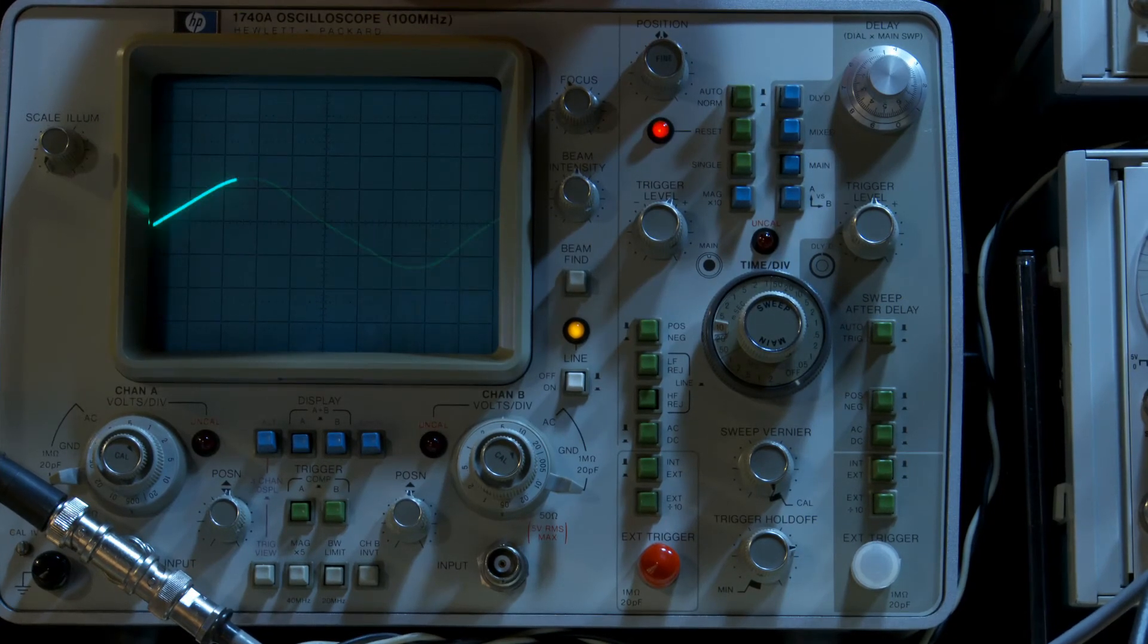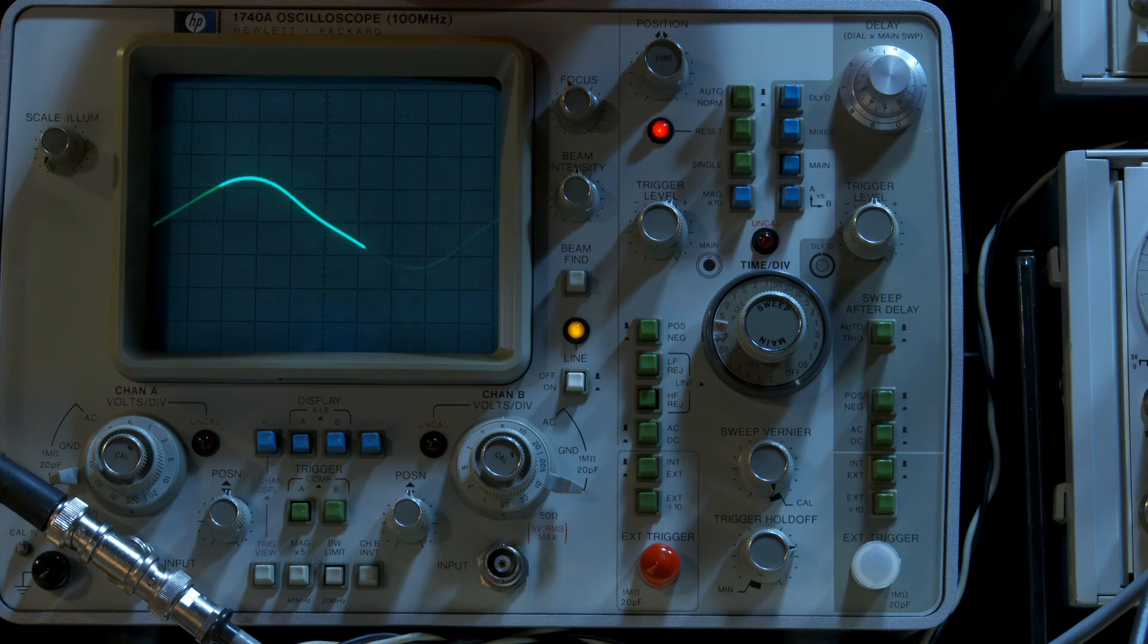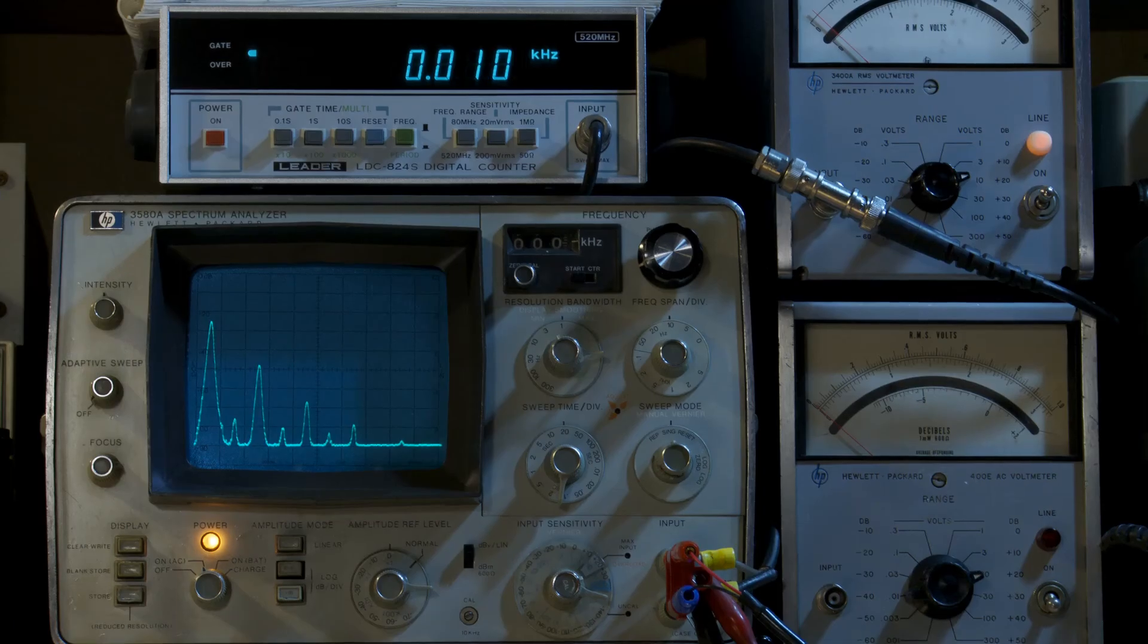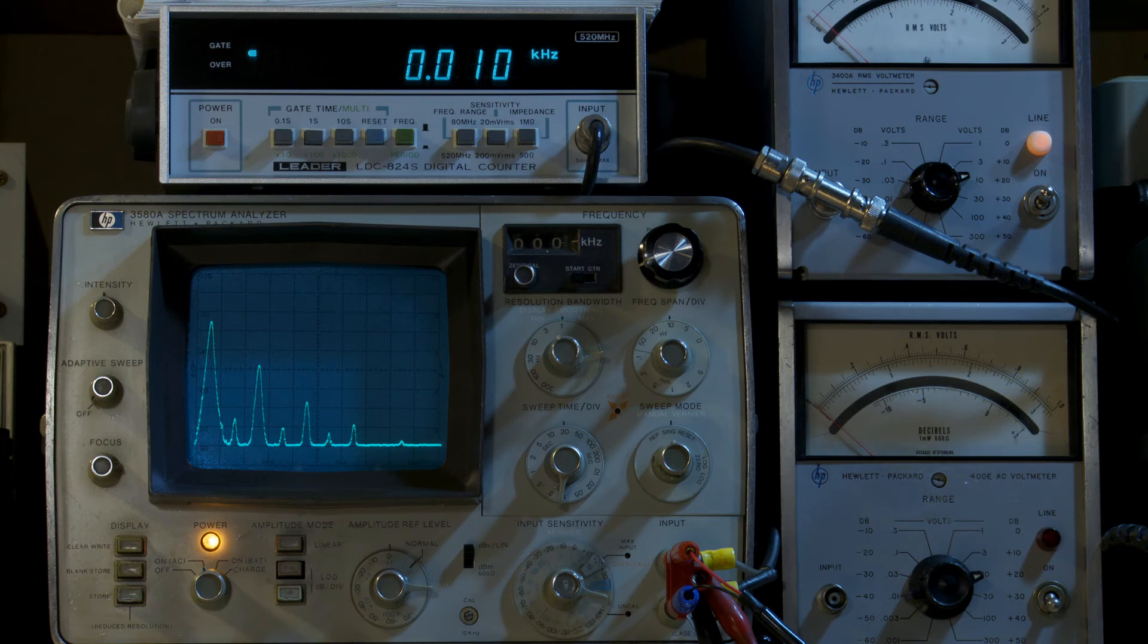Our sine wave is not so sinusoidal anymore. More like a rounded-off triangle wave with a notch. Distortion is rife with odd-order harmonics and some even-order harmonics. Definitely not a euphonic-sounding set of amplifier stages.